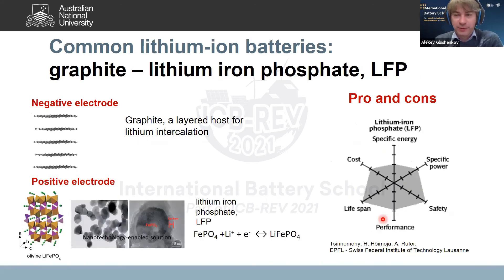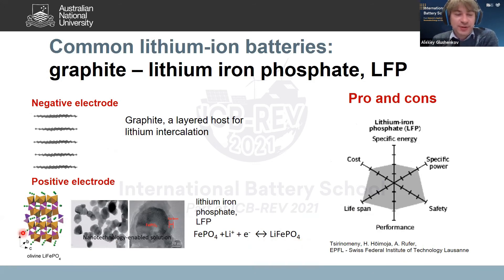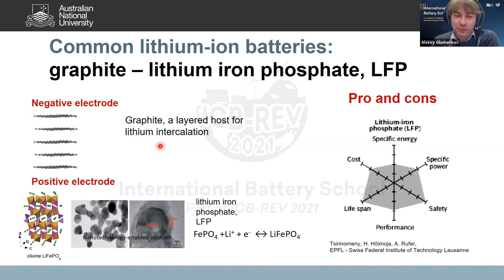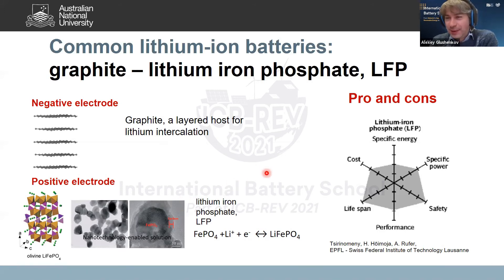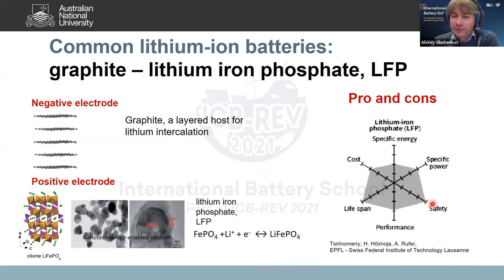Graphite/LFP batteries are also widely available. Here, the positive host is lithium iron phosphate, which has a structure with tunnels where lithium ions sit and can be extracted and replaced. This material requires nanotechnology-level control — you must create small particles and likely use carbon coating or dopants to improve conductivity. Comparing with NMC: specific energy is smaller in LFP, but there is a clear win in lifespan — these batteries keep going and going — and you also have an advantage in safety.